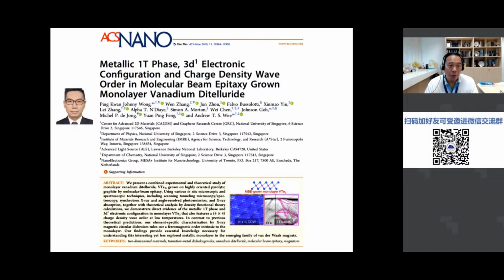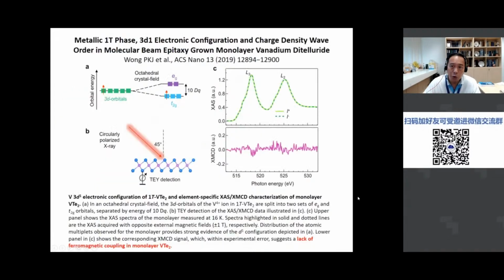So Johnny went on further to work on the sister TMD, vanadium ditelluride, right? That's very similar. And not surprisingly, in this case, there's some STM and ARPES data, but I just wanted to show you the XMCD data. Again, the XMCD signal is basically zero. The difference spectrum between the two helicities is zero. So we also deduced that this VTe2 is non-magnetic, which then further supports our initial observation.